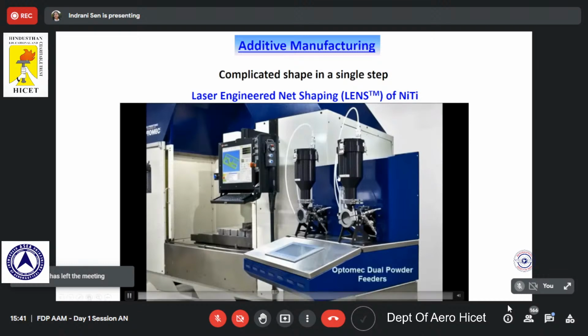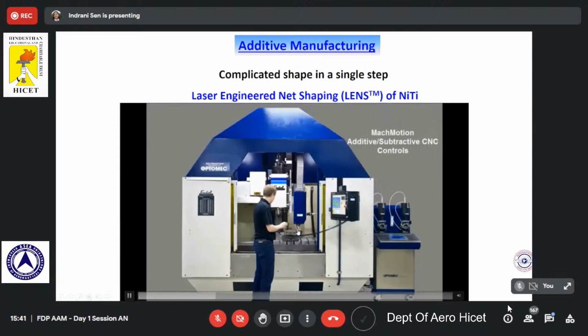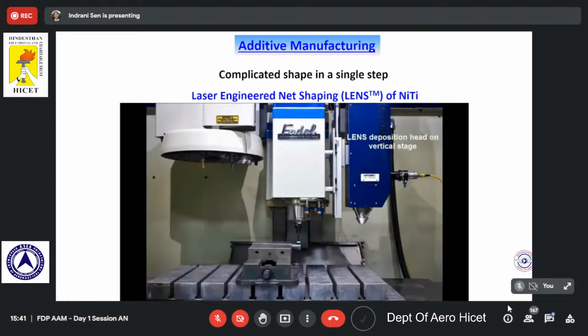So you can see that there are these dual powder feeders. Here is the laser tip. Now you can see the parameters set on the machine. The laser is on, and this is how it is being formed. You can see the powder feeders and then the laser, and this is moving, scanning as per the design. It is moving in this direction, and in the next layer you will see that it is moving in a perpendicular direction. Now you see it has changed its direction of moving to a perpendicular one.